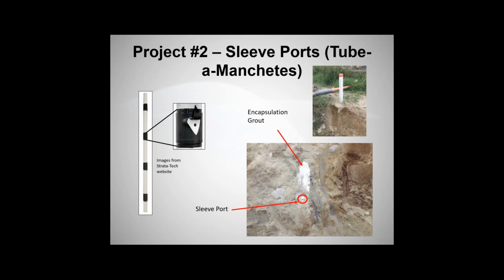It allows you to inject in specific spots, again, so that you can control where your material's going. Not the greatest picture, but here the red circle shows a sleeve port that's been excavated. The white stuff around it is an encapsulation grout that's around it when it's installed. And then, as you can see at the top picture, a sleeve port is simply PVC sticking up above the ground.